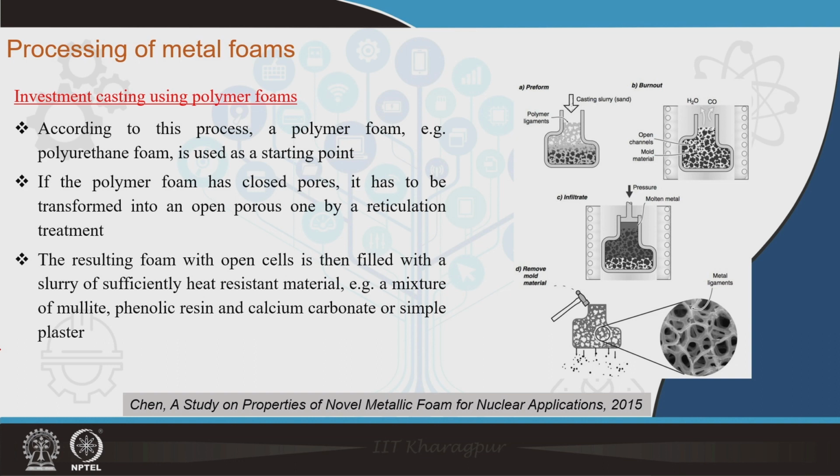So, now the next task is that the pores between the plaster struts have to be infiltrated, and very often this infiltration is not an easy task, because the polymer struts or the polymer cells have a very fine dimension, and it is not always easy to infiltrate, because it is filled with air. That is why, as we discussed yesterday, the first step always is that very often this porous plaster scaffold is put under vacuum, so that all the air is sucked out